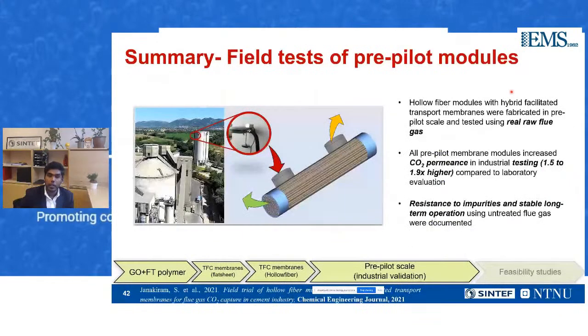So with this, we saw that these membranes, which are hollow fiber modules of facilitated transport membranes, they were tested in real flue gas. And the CO2 permeance in the testing site was actually 1.5 to 1.9 times or double that respective of the laboratory scale test.